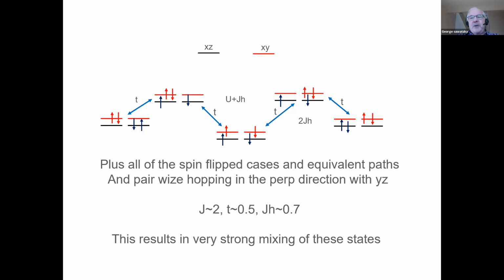Yeah, well, I showed you pictures in LDA plus U with LSDA, where you actually have 3 Bohr magneton magnetic moments, depending, but then the lattice is also very stretched. It would automatically want to stretch, and the selenium would want to come down into the iron plane almost. You'd almost get a rock salt like structure in the end. But these moments, we feel, are really quite large. So what we get is something close to 2 Bohr magnetons, which means a spin of 1, right?